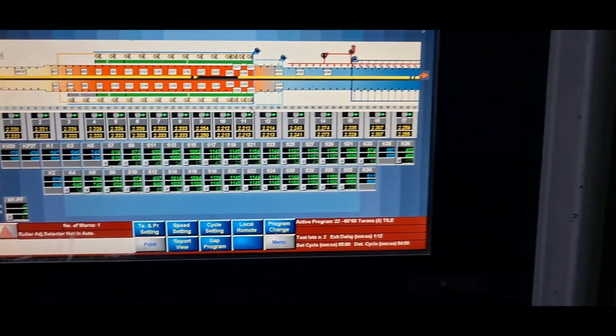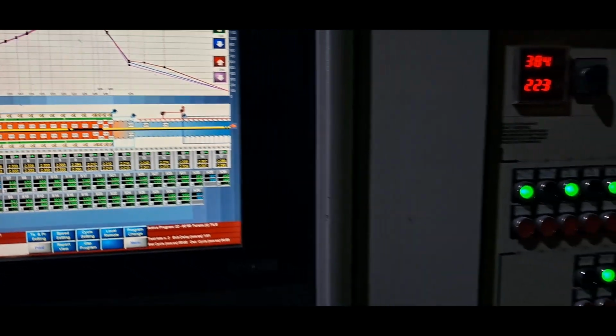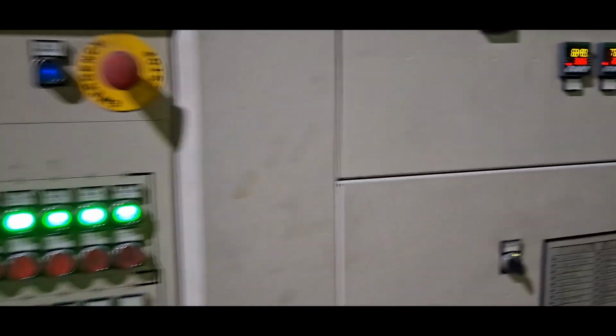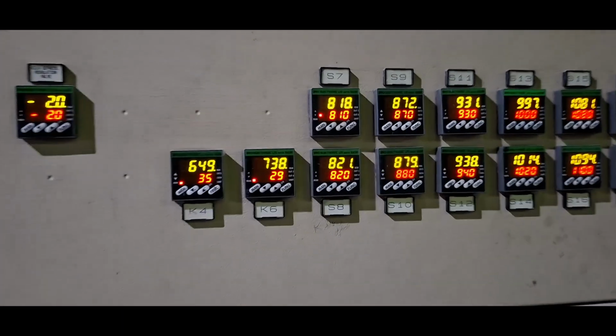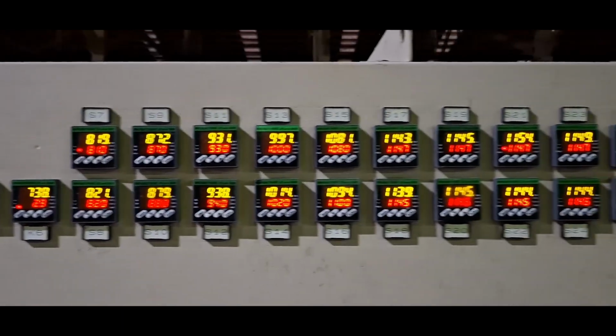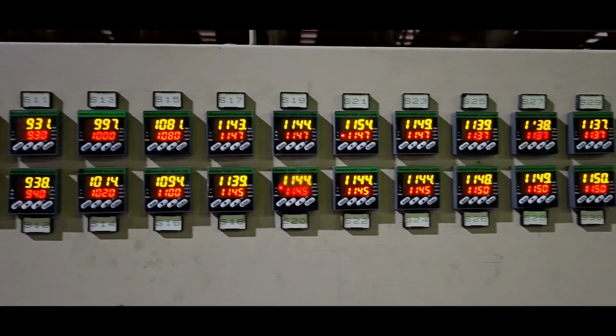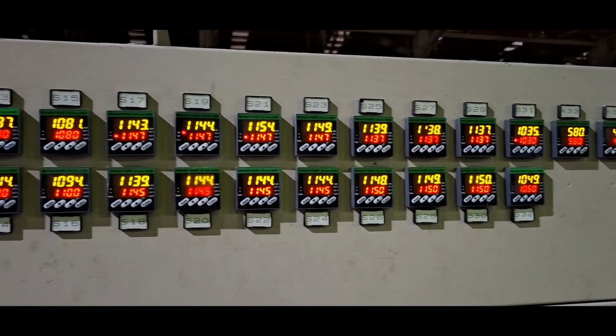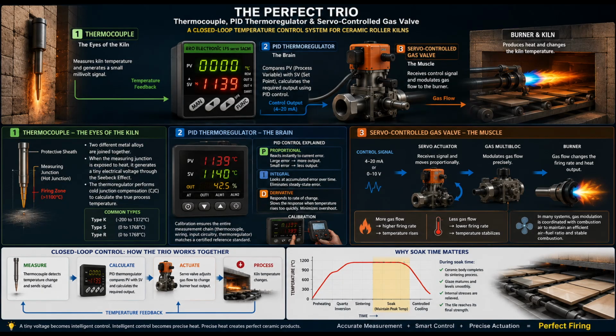In an industrial roller kiln, this process doesn't happen in just one place. The kiln is divided into multiple independent heating zones. Each zone has its own thermocouple, its own PID Thermo-Regulator, and its own servo-controlled gas valve. The thermocouple measures the temperature. The PID controller calculates the correction, and the servo valve adjusts the gas flow, all in real time. Every control loop works independently, but together, they create the precise firing profile needed to produce consistent, high-quality ceramic tiles from start to finish.